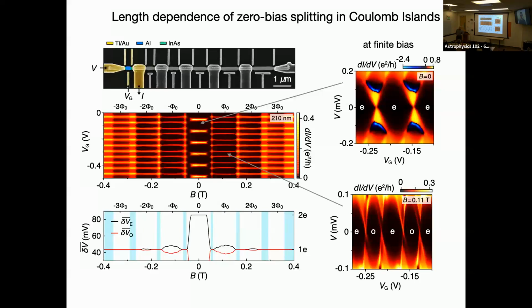So what happens when you make a wire that's a Coulomb island instead of a long one-dimensional wire? Well, it depends on how long it is. Let's start with a really little one. That's the smallest wire. It's an NISIN cylinder. And now we can thread magnetic field through the cylinder. And if we go to 0 magnetic field, 2E Coulomb blockade. You have to tilt your head sideways a little bit because this is now the gate that makes Coulomb blockade. So this is a Coulomb blockade peak, another Coulomb blockade peak, another Coulomb blockade peak, spaced by 2E.